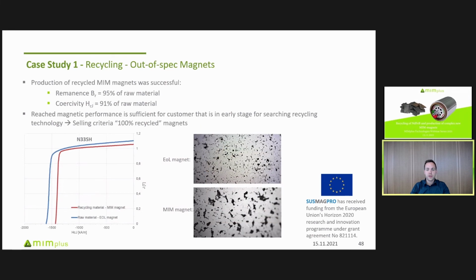If you have a look at the magnetic properties of the MIM magnets, the whole process was quite successful. You see here the starting grade was the N335H. The blue line is the hysteresis curve of the part, and the red line is the properties we reached with the MIM parts. So we can say we can reach, in this case, a remanence of 95% of the raw material and a coercivity of 91% of the raw material. And the microstructure of the MIM magnets is well comparable to that of the end-of-life magnet, the present sintered magnet, because we have sintered magnets but shaped in a more complex way. For our customer, this was quite sufficient because he just wanted to have the selling criterion of 100% recycled permanent magnets in his product. And you see here, it is reached easily.